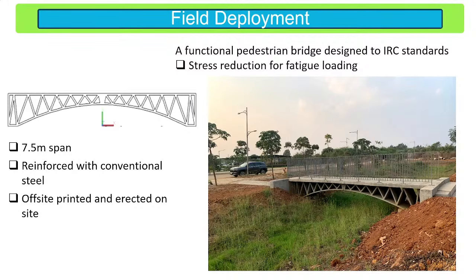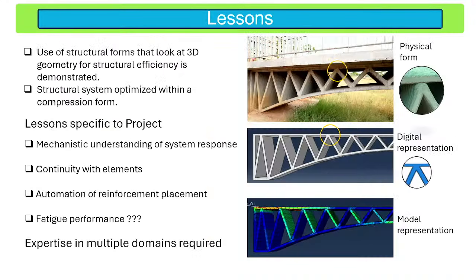The few places that we kind of cheated was, I don't know the fatigue response, and that becomes very, very critical, particularly for bridges. So we did what the code allows us to do, and that is to use a lower allowable stress in our design. And remember, the compressive strength I'm using is already a low value, the lowest compressive strength of all three directions, while I'm loading the material in the strongest direction. So there is already an inherent factor of safety built in there. On top of that, we took further reductions.